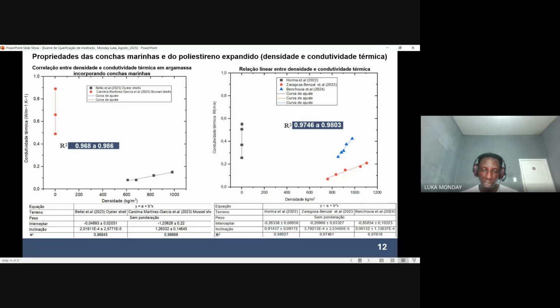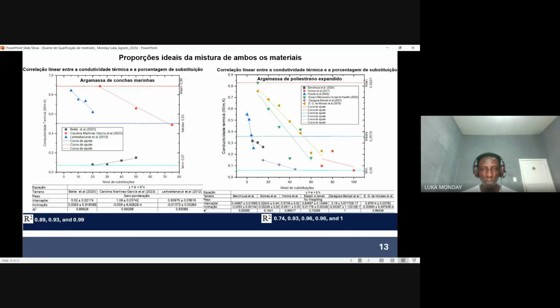In the same way, using the expandable polystyrene, an R square of about 0.97 to 0.98 was also obtained, which clearly shows that yes, density plays a key part using both materials. So as the density tends to decrease, the thermal conductivity of this material also tends to decrease, and the reverse is the case. While considering the level of substitution of both materials also matters with respect to the thermal conductivity of these materials. As the substitution level increases, the thermal conductivity of this material decreases, and vice versa. The reverse is the case for both materials.